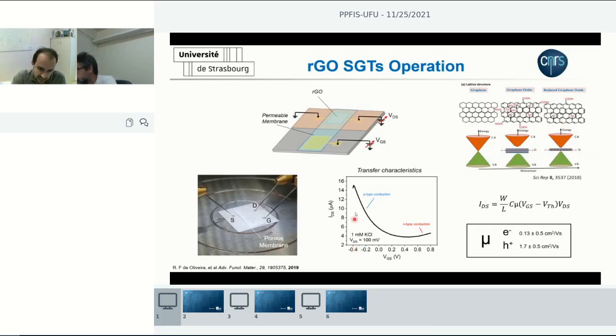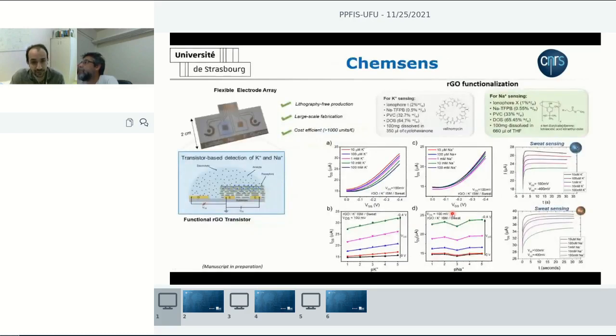An ambipolar material, meaning that when the gate voltage is negative, we have conduction via holes, so it's a p-type conduction that reaches a minimum current value and rises up by presenting an n-type conduction. By doing the math, we can extract the charge carrier mobility both for holes and for electrons. So again, this is how to use this kind of device architecture to measure the electrical properties of thin films, in this case, semi-metal reduced graphene oxide.